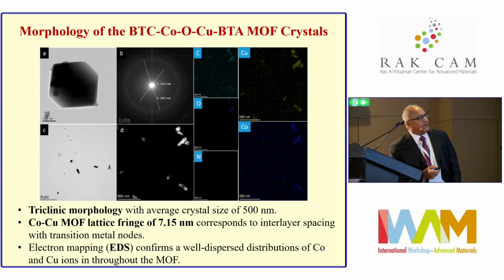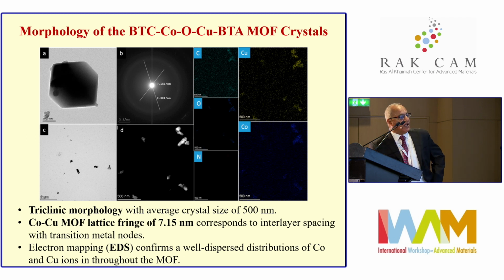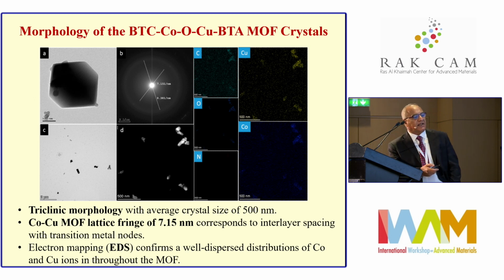From X-ray diffraction and TEM, we can get information on the morphology of the crystal. So we see that this belongs to a triclinic morphology with an average crystal size of 500 nanometers. And the cobalt-copper lattice fringe distance is 7.15 nanometer, which corresponds to the interplanar separation with transition metal nodes in this type of framework. And also the electron mapping, unfortunately, is not showing very well here, shows that the structure has a very good distribution of cobalt and copper ions throughout the framework.